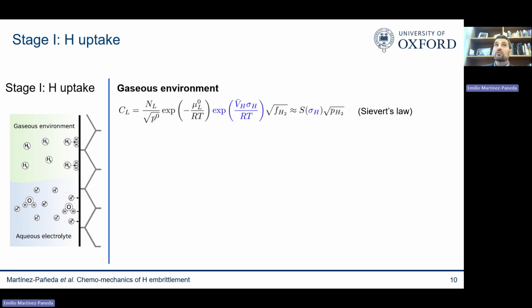The good news is that for a gaseous environment, under steady state conditions, we do have a closed form solution. This is what we call Sieverts' law, and it relates the quantity I'm interested in, the hydrogen concentration at the surface, with the quantity described in the environment: the hydrogen pressure, something I know or define as an engineer. The only thing connecting them is the material solubility, which I can identify easily with a permeation test.